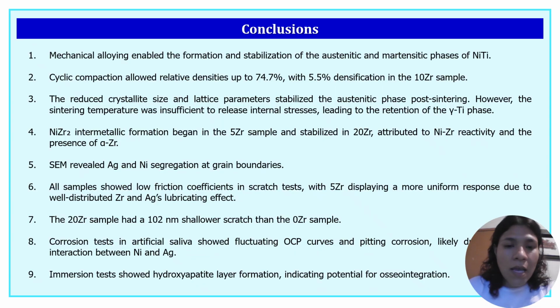In conclusion, mechanical alloying enables the formation and stabilization of austenitic and martensitic phases of nickel titanium. All samples show a low friction coefficient in the scratch test. The 20 zirconium sample had a scratch 102 nanometers shallower than the 0 zirconium sample. Corrosion test in artificial saliva showed fluctuating OCP curves and pitting corrosion caused by the interaction between nickel and silver. Immersion test showed hydroxyapatite layer formation, indicating potential for osteointegration.